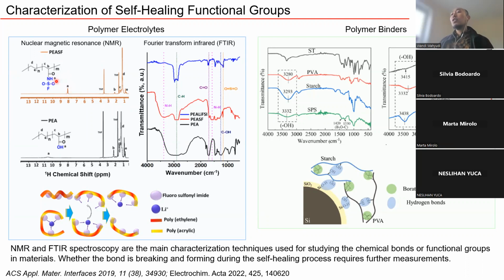And later on, they change the hydrogen atom with lithium, and they show this transformation by using FTIR, where these NH groups disappear in this type of polymer electrolytes. In other literature, the authors synthesized the polymeric binders, and they showed that the presence of OH groups in the polymers also exists in the silicon electrodes. However, it is important to understand whether these functional group bonds are breaking and forming during the self-healing process, which requires further measurements.